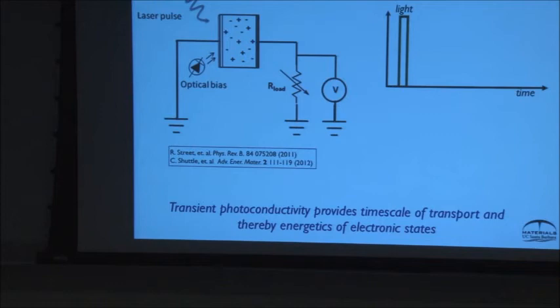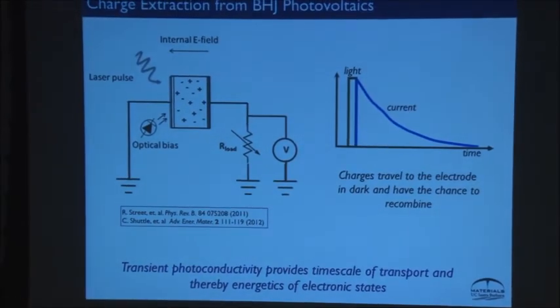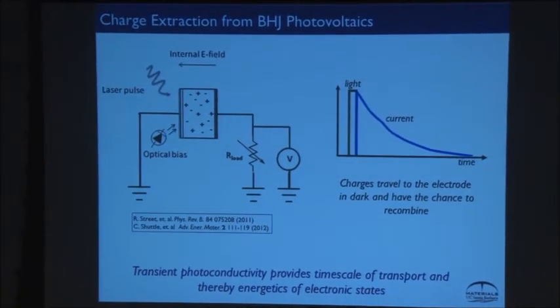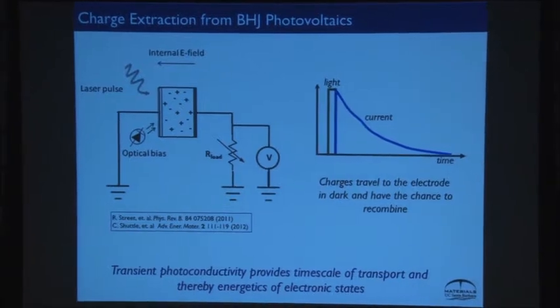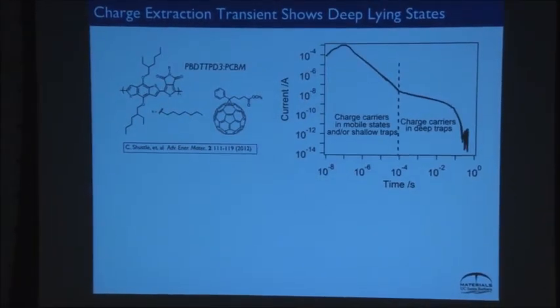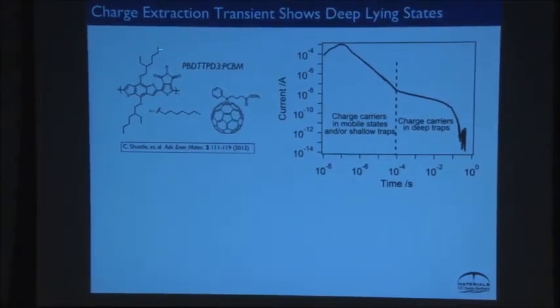But when you go do an experiment like this, where I send a light pulse in, turn the light off, and just watch the current leak out, they're both highly efficient cells, so you might expect they should have similar mobility lifetime products, everything should be good. But if you look at this material, which has drawn a lot of interest, what you actually see in the charge transient, when you go out to very long times, is that charges just keep leaking out in the millisecond regime. You only have to go 100 nanometers, okay? So obviously, it seems weird that it would take that long to get out.